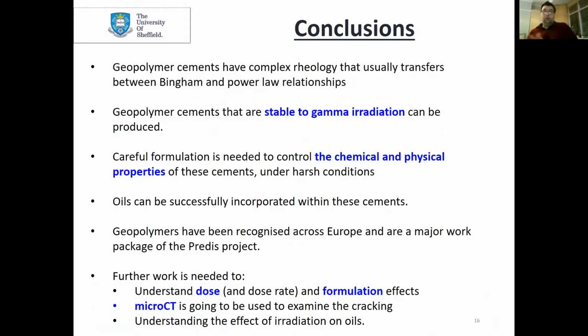So just to conclude, I have shown that these samples are stable under gamma irradiation. Careful formulation does need to be undertaken in order to control the chemical and physical properties of these cements under the harsh conditions of gamma irradiation.